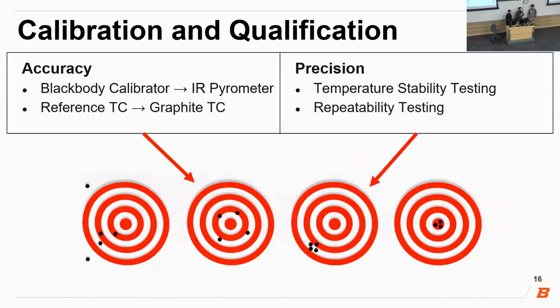After modifying the furnace, we had to do a series of calibrations and qualifications. To verify the accuracy of the furnace, we did a calibration with our black body calibrator on our IR sensor, and using a reference TC, we verified our graphite TC. To verify precision, we also did a couple of tests: temperature stability of the graphite sample at each temperature set point, and repeatability testing using the same sample.